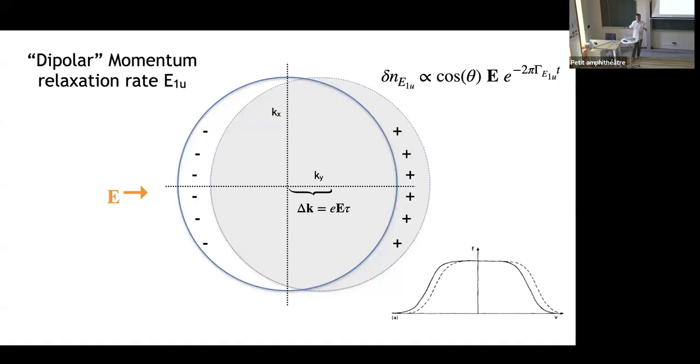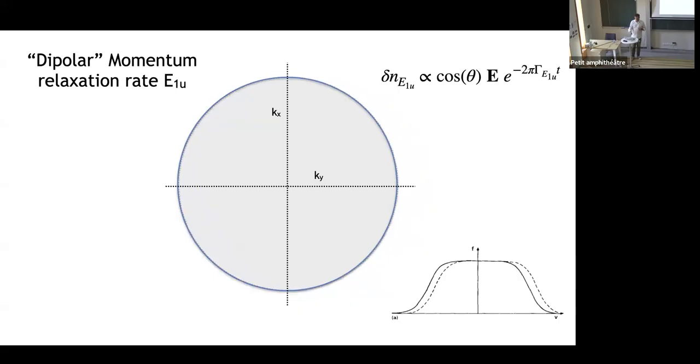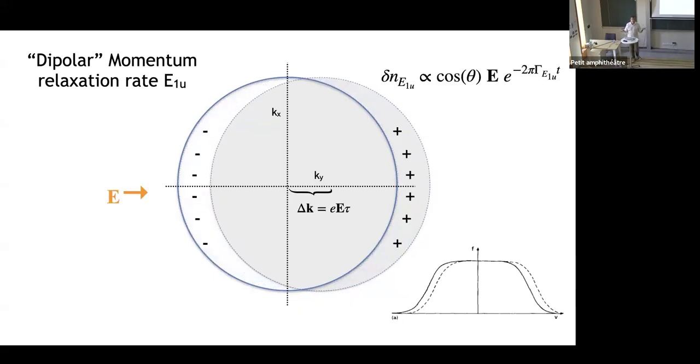We take a Fermi surface, we shift it sideways, and then we let it decay, and it comes back to the origin. That's a state of finite momentum. And so if that's going to decay, the electronic system has to lose momentum. The only scatterings which allow this to return to zero momentum are scatterings which remove momentum from the electronic system. And what does that in conventional electron theory? Electrons coupling to impurities, Umklapp scattering, electrons coupling to phonons. Those are our choices in conventional theory, simple Ashcroft and Mermin physics.